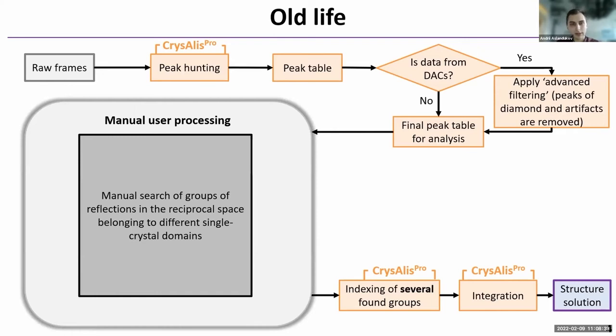So usually the typical procedure of data processing in the case of polycrystalline samples is the following. After peak hunting in programs such as CrysAlisPro, we get a peak table which contains all coordinates of our reflections. Then in the case of high pressure data, it's possible to apply advanced filtering to remove diamond peaks. And then the most important, we need to perform manual search of groups of reflections in the reciprocal space belonging to the different single crystal domains. And only after such manual procedure, we can index all of these found groups and perform integration and structure solution.